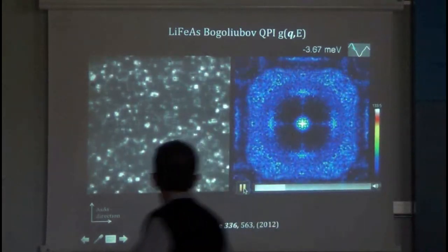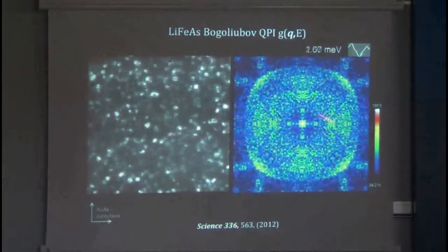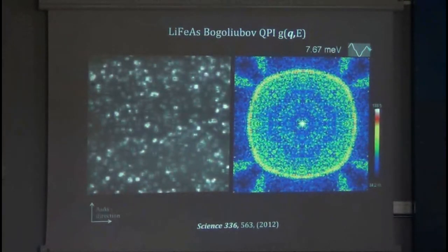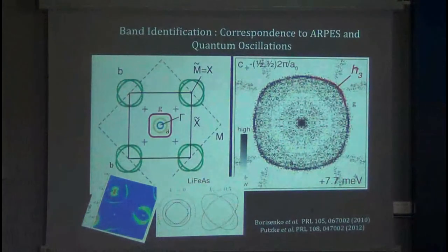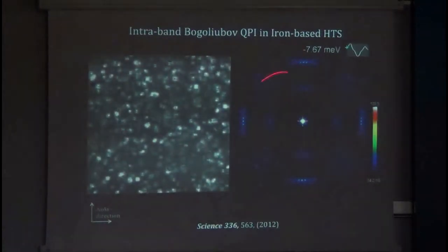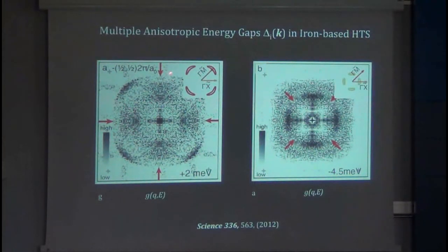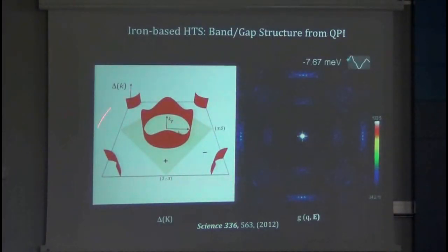If you know what you're looking for, there are three bands here, and each of them is gapped. One, two, three. We can process this scattering interference information. We have knowledge from photoemission and quantum oscillations of which band is which, and there are five bands in the first Brillouin zone of the iron superconductors. But from the quantum oscillation and photoemission data, we're able to tell which band we're looking at. And from this data that I just showed you and a model of how scattering interference would produce different signatures at different bands for different superconducting energy gaps, we're able to extract the momentum space structure of the superconducting energy gap, which is highly anisotropic.